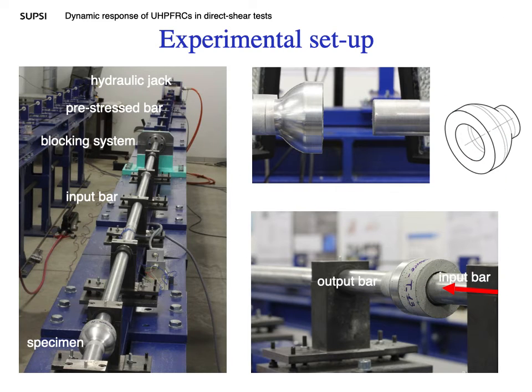high strain rate tests in direct shear have been carried out by means of modified Hopkinson bar in compression. The system consists of two circular aluminum bars having a diameter of 30 mm and a length of 3 meters for both input and output bar. The specimen is sandwiched between the input and output bars through the special connector designed to maintain acoustical impedance constant in order to avoid spurious reflection in the interface.